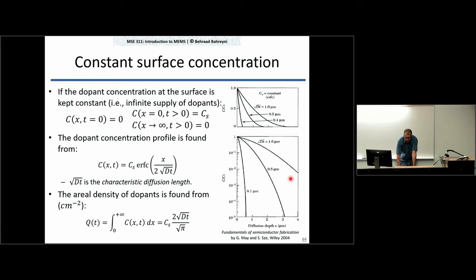So the areal density of dopants can be found from this expression. Again, depending on the time and temperature, temperature determines D, and time gives your characteristic diffusion length, you get increasing numbers of dopants into your substrate.